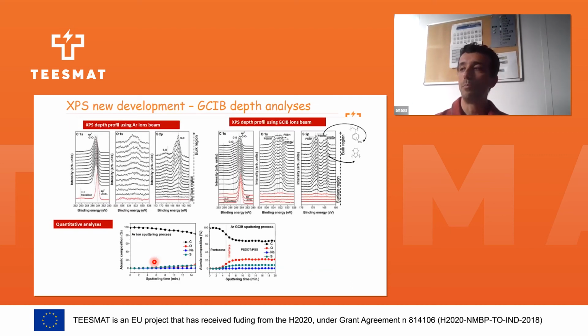Here I give an example of PEDOT:PSS, which is not battery-based material, but is solar cell-based material, which is used as a heterojunction in organic photovoltaic cells. And we make a stack of PEDOT:PSS, and on the top we deposit a graphene-based structure. And we use two kinds of depth profiling, ionic depth profiling and GCIB depth profiling, on the same sample, just to show you how the damage is when we use ionic-based depth profiling.